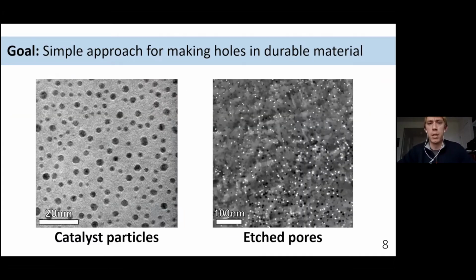So just so you have an idea of what this looks like, these are a couple of TEM images where on the left side we have silver catalyst particles deposited on a very thin silicon film, in this case only a couple hundred nanometers of thickness. And on the right side, this is following that metal-assisted chemical etching approach, where on the left, the dark contrast is actually the metal catalyst. And on the right side, the light contrast features are actually the holes or pores that are punched through that silicon film. And I do apologize, the scale's a bit mismatched here, but you can get an idea of how the size of the particle actually translates pretty closely to the size of the pore in that silicon film.